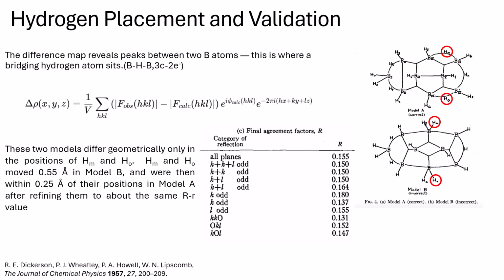By overlaying these residue peaks onto the known boron skeleton, Lipscomb could assign hydrogen positions with high confidence, and the plausibility of this placement was confirmed through bond length analysis and refinement analysis. So as you can see in the equation here, the delta rho represents the change of electronic density in two different maps, and it indicates the possible position of the hydrogen atoms.